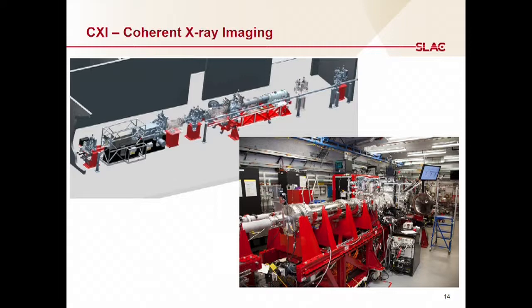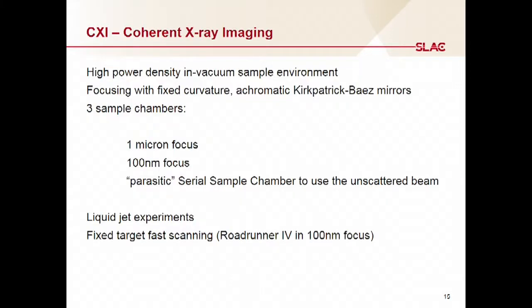instrument is the Coherent X-ray imaging instrument, which is the CXI. CXI is very special because it is the only hard X-ray instrument that has KB focusing optics. So what this can do is that you can get the highest power density that exists at LCLS at this instrument. It has fixed curvature achromatic KB mirrors. There are 3 sample chambers. One is the 1 micron focus using the 1 micron KB mirrors. There's the 100 nanometer focus using those KB mirrors. This provides the highest power density that exists at LCLS.